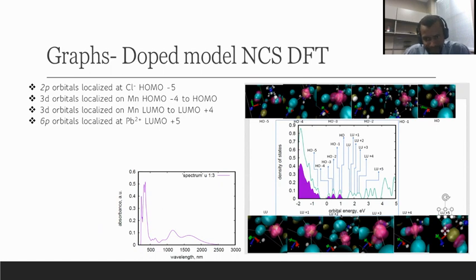So in your spectra, all the peaks from like 500 to 2000, those are d-d excitations. Yes, this is the one that I truly didn't understand myself. So I obtained the spectrum from the non-collinear spin DFT with the doped model. And yes, I used the oscillator strength from all of the transitions that we had there, and plotted the spectrum from 150 nanometer to 3000 nanometer to see how it's going to look. But this is what I found, and to be honest, I'm not sure if I understand this nicely.